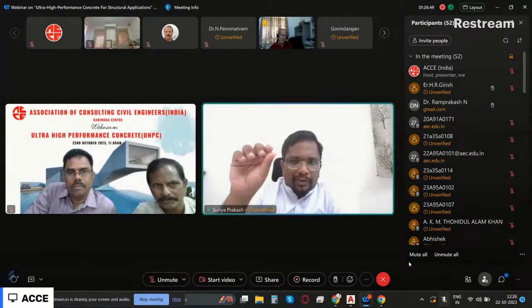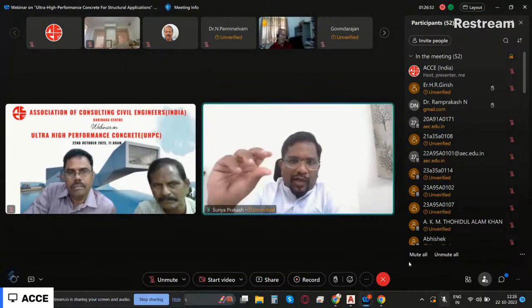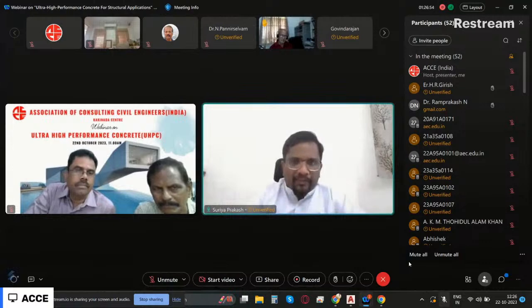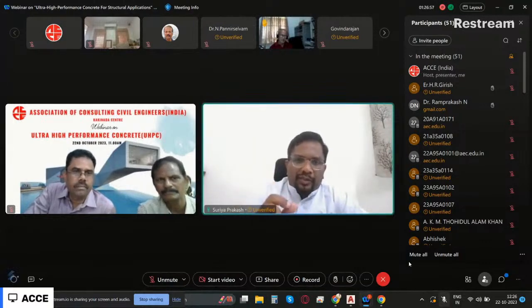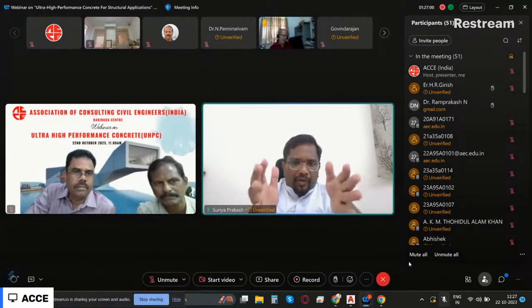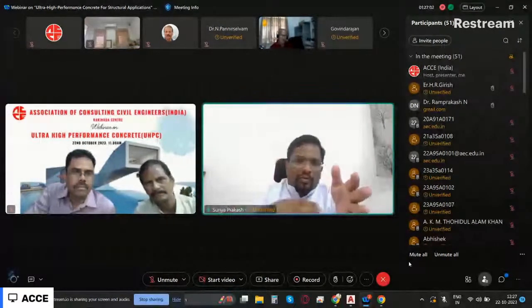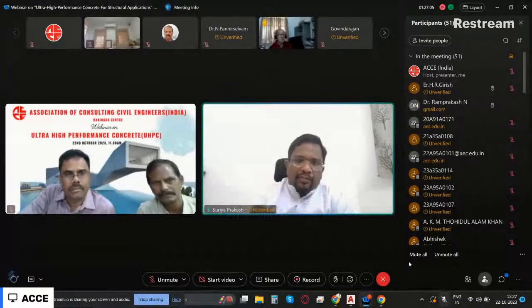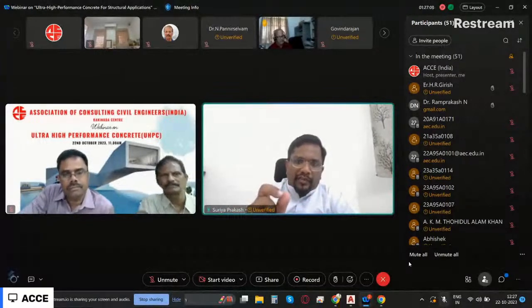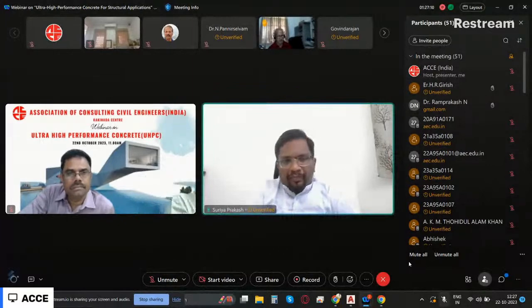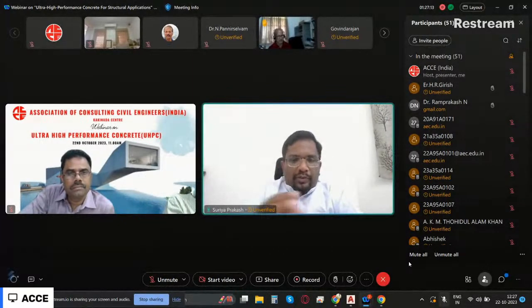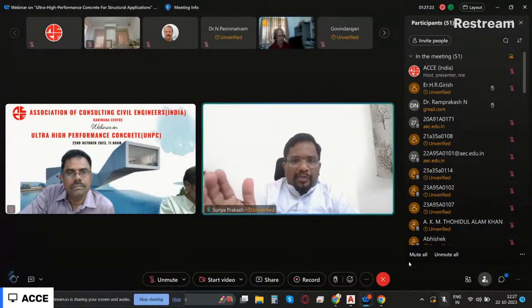The aggregate sizes are usually limited to 2 mm. If I go for a large size aggregate, then I cannot get that packing. So that is the reason we are limiting the maximum size. The whole idea is that in a particular volume, I want to pack as much material as possible. That is possible only if I limit the size of the aggregate. But now people are also using 5 mm, 6 mm aggregate. There you have to really tweak and make sure that you achieve the packing you want. But typically in UHPC, the size of the aggregates is less than 2 mm.